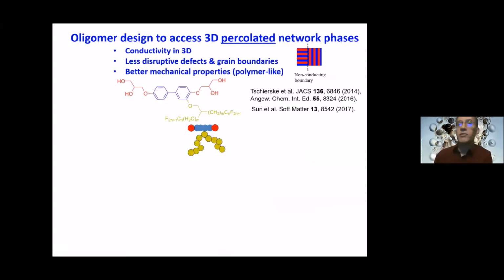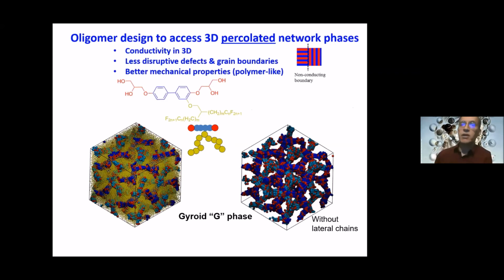And there are some oligomers, like the one shown here, which is known as a bolaamphiphile. And you can see that it contains 3 chemical groups. Shown in red are these glycol systems. You have this biphenyl rigid core in the middle, and you have this side chain, which is sort of perfluorocarbon. So these two are hydrophobic. This one, the red, is hydrophilic. Now, this material has been shown by experiments and simulation to assemble into this structure, which is using basically the color scheme in this coarse grain representation. And that gives you an idea of this sort of 3-dimensional structure. So this is known as a gyroid, as a G phase.